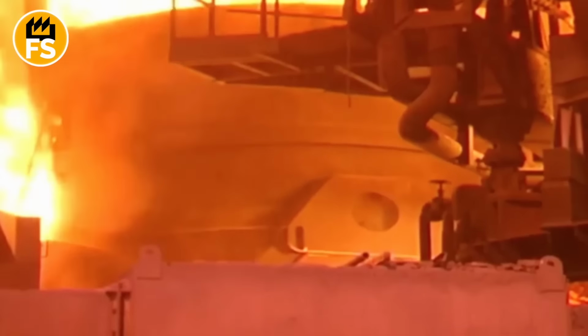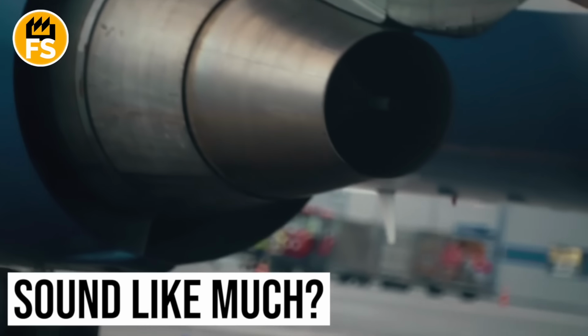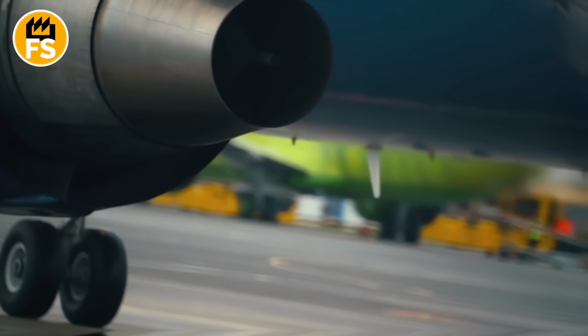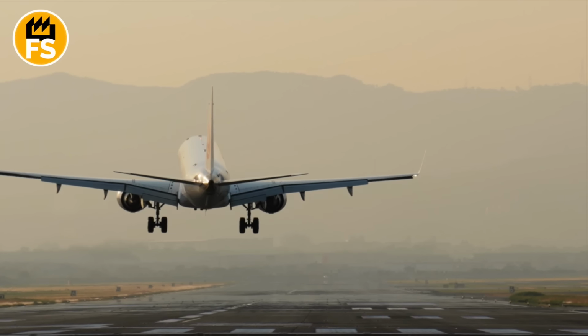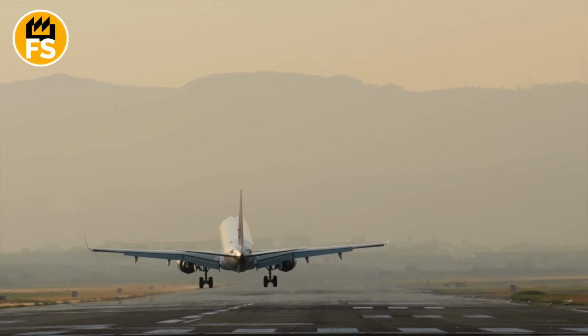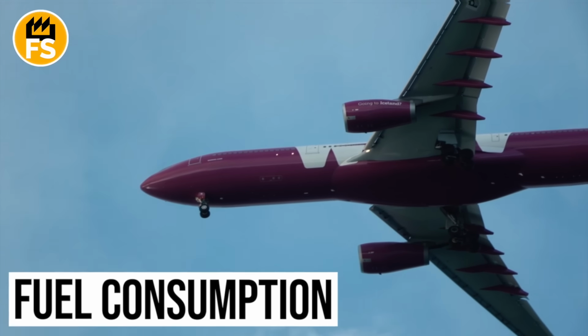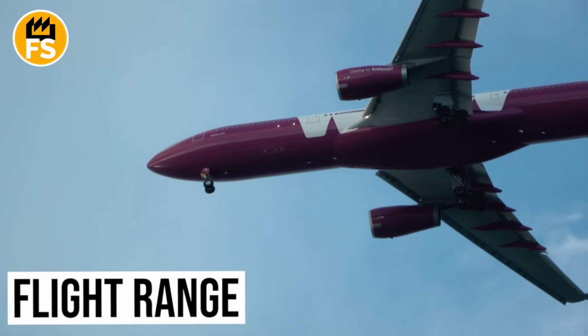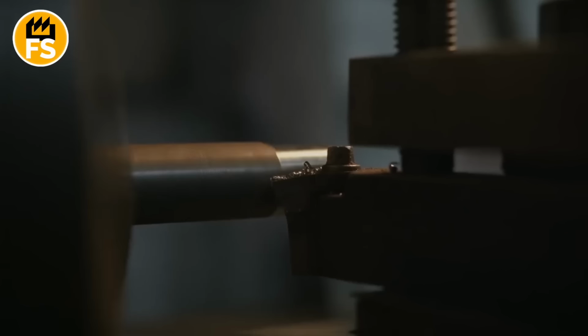Adding just 3% rhenium to a nickel superalloy increases the operating temperature by about 54 degrees Fahrenheit. Doesn't sound like much, but in jet engines, every 18 degrees of additional temperature gives roughly 1% increase in efficiency. And efficiency means fuel consumption, flight range, airline economics.